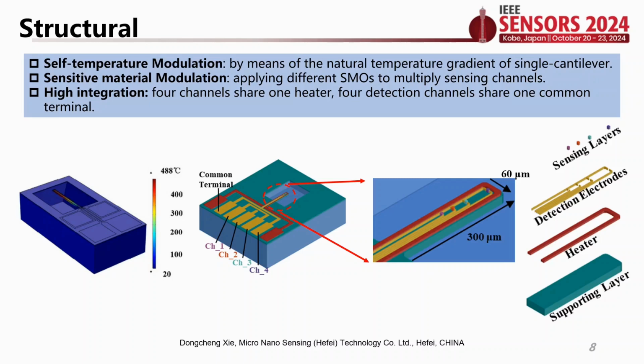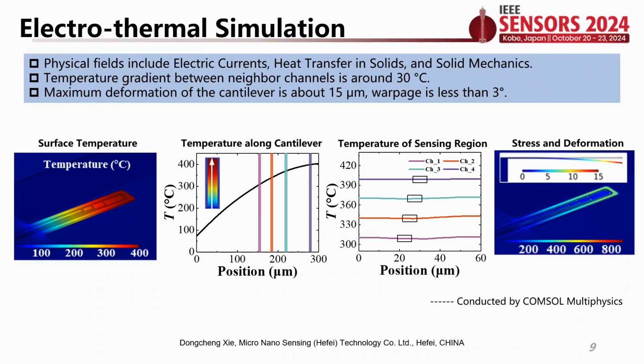which combines self-temperature modulation and material modulation. Four detection channels with a common terminal share one heater. As usual, we did electrothermal simulation using COMSOL Multiphysics to verify and optimize the design. By adjusting the positions of the sensing regions, the temperature gradient between different detection channels is about 30 degrees, while the maximum temperature is about 400 degrees Celsius. And the deformation of the cantilever is about 15 micrometers.